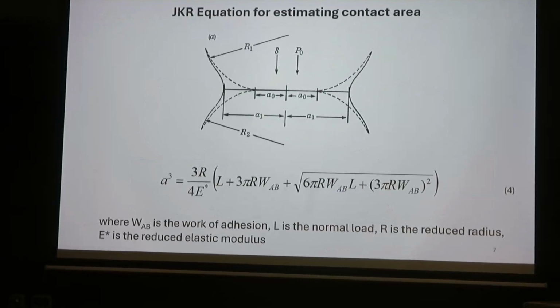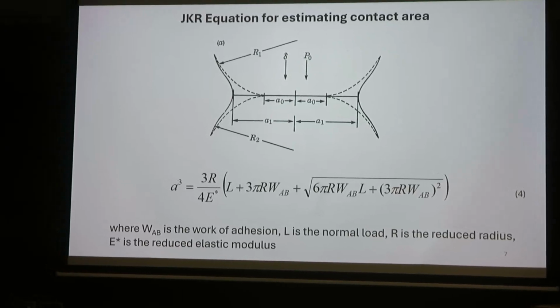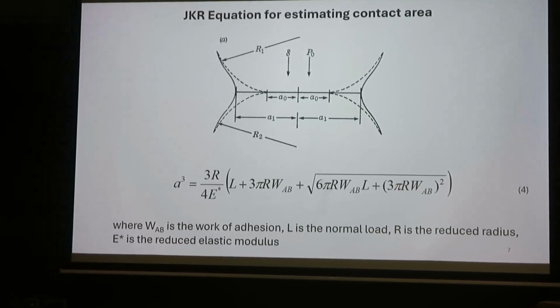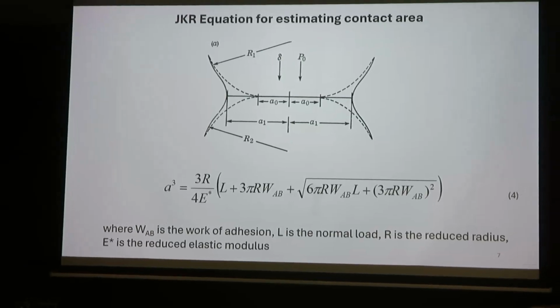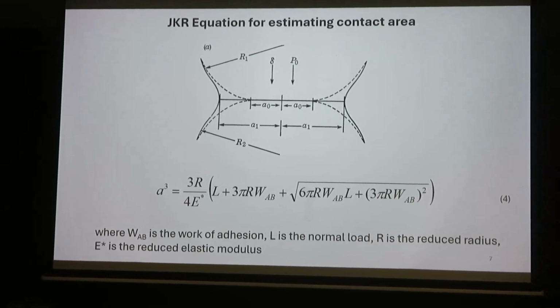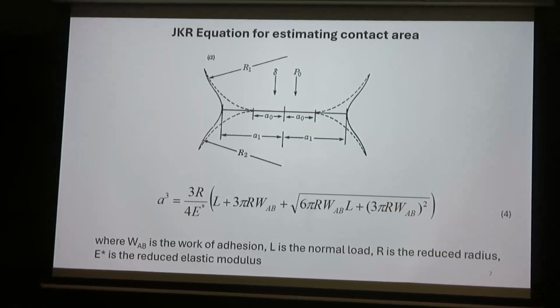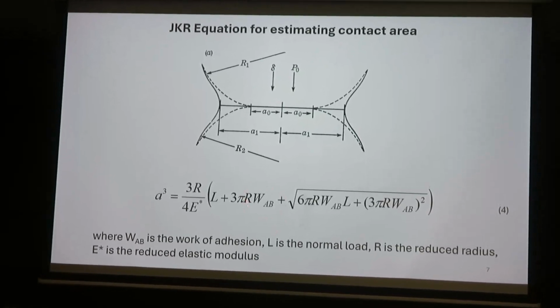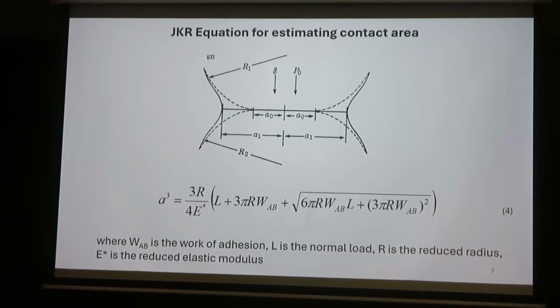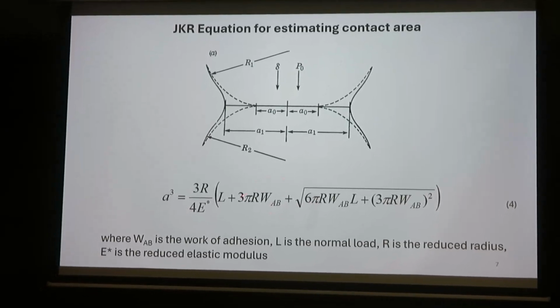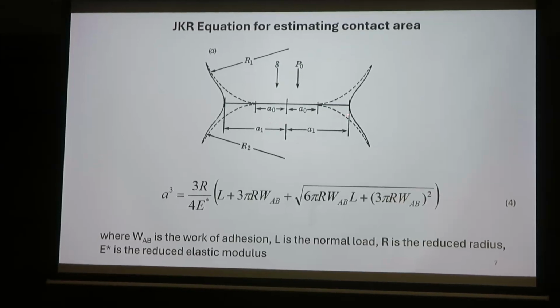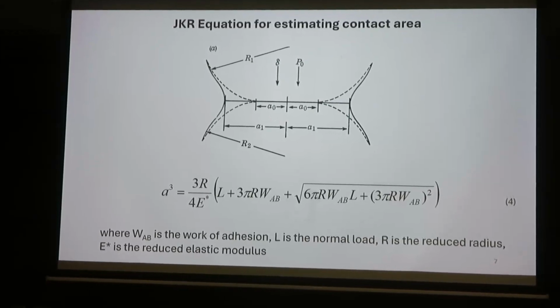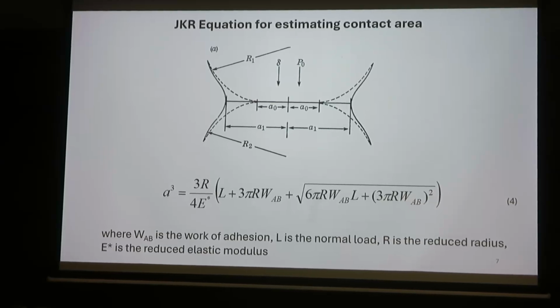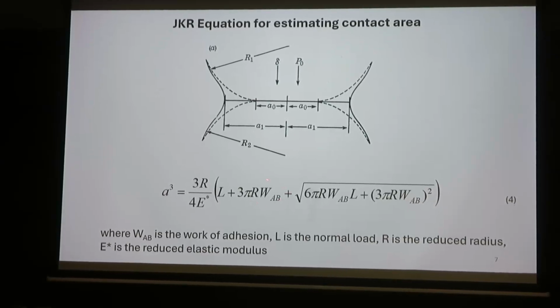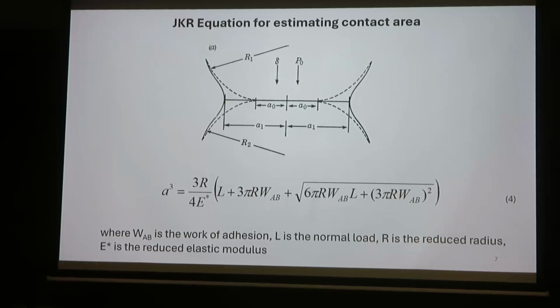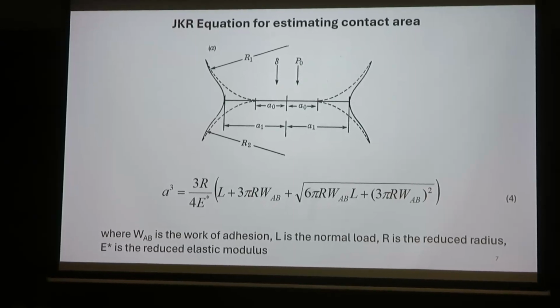In the case of polymers, as well as in the case of metals, but for polymers this is very, very important, we have to use the JKR model instead of the Hertz equation. And the difference is that in the JKR model, we have this work of adhesion. Work of adhesion is included in the equation for contact area. So if we are going to calculate contact area, and contact area is very, very important for us to calculate, so the work of adhesion is very, very important. So here we can see the relation between work of adhesion and friction.